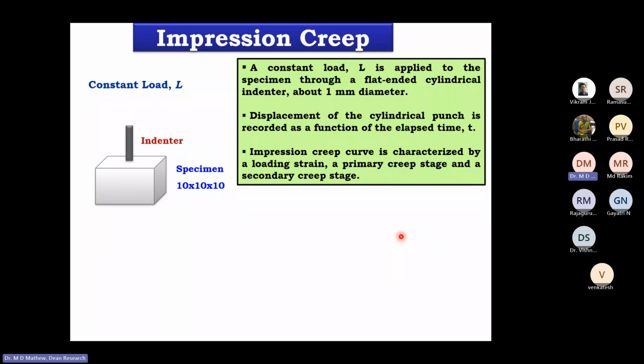As the term itself tells us, the creep deformation is determined under compression loading. What we do here is, at a constant load, the creep means what? The deformation that happens at a constant load at a constant temperature. The deformation as a function of time is the creep curve.